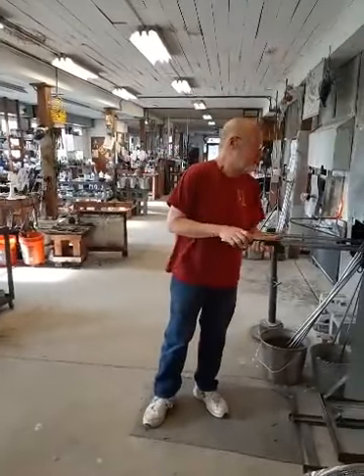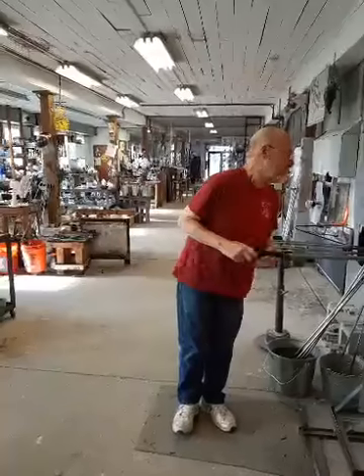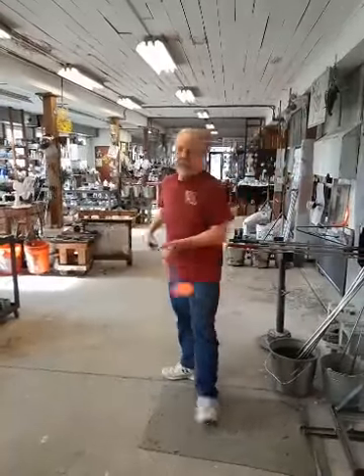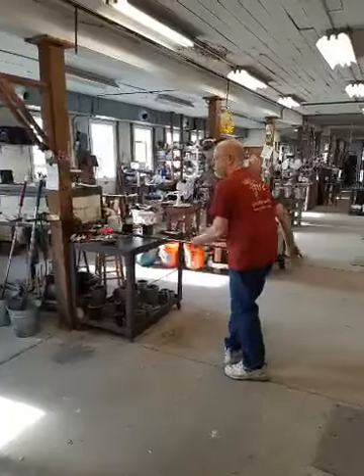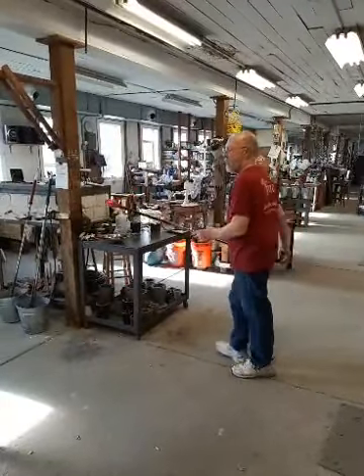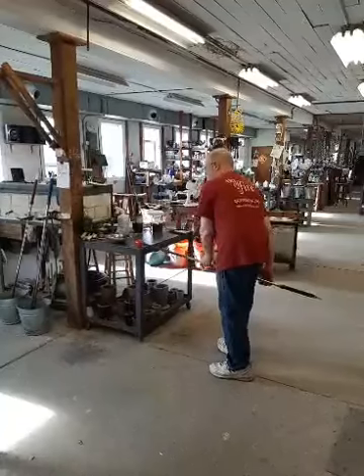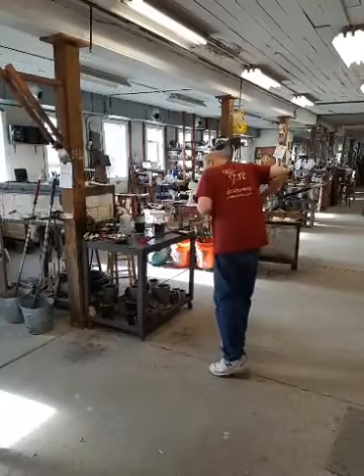So if he cuts the jack line too close to the pipe, the glass doesn't hang down into the mold. So that's always a trick in something like this, is to make sure you've got that. So he's gonna get a volume of air in that, and then after his next heat, he'll probably begin working on shaping of the glass.